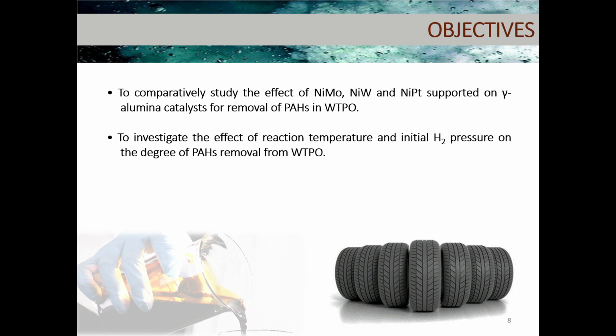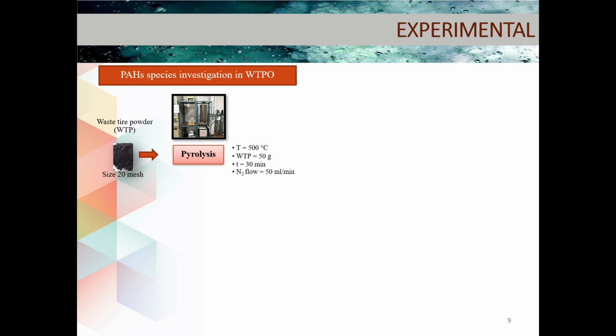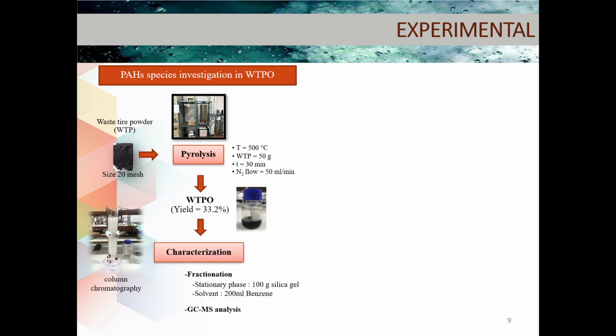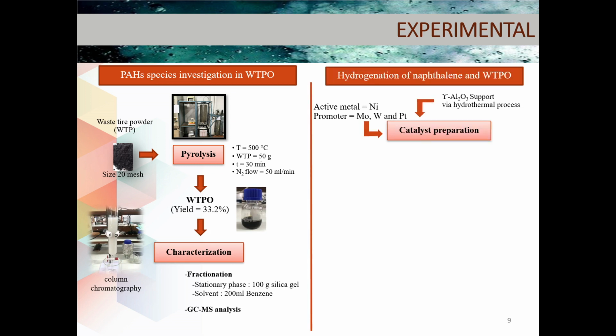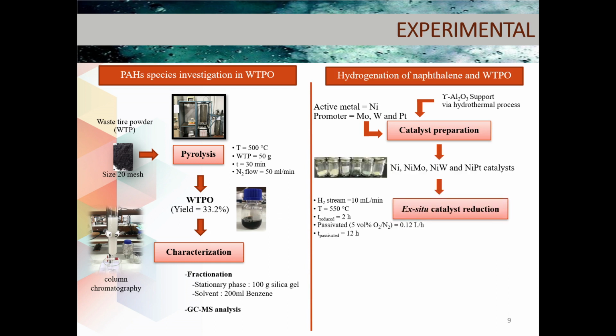We also investigate the effect of reaction temperature and initial hydrogen pressure on the degree of PAH removal from WTPO. In the experiment, we divided the work into two parts. The first part is the identification of the PAH compounds in the WTPO by using GC-MS and fractionation by column chromatography. Then, when we know the main compounds inside the WTPO, we use them as model compounds and hydrogenate them to investigate the suitable catalyst before applying it to the hydrogenation of the WTPO.